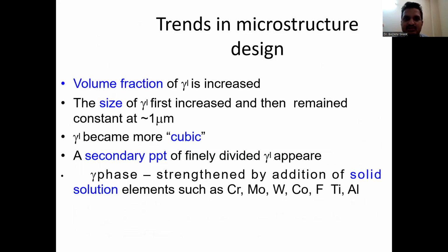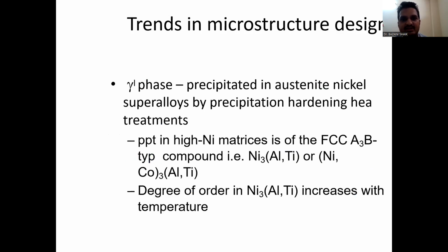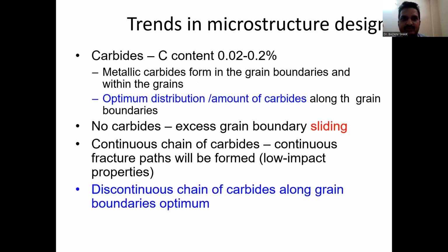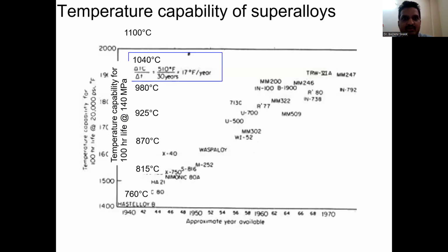And there are trends in microstructure design and how they improved, and the different additions involved, like solution strengthening with chromium, molybdenum, cobalt, titanium, and these are the different phases, and the degree of order increases with respect to temperature. And these are the carbides, with carbon percentage content generally low, with an optimum distribution of carbides. These carbides sit on grain boundaries and resist sliding, and there is a discontinuous chain of carbides along the grain boundaries.